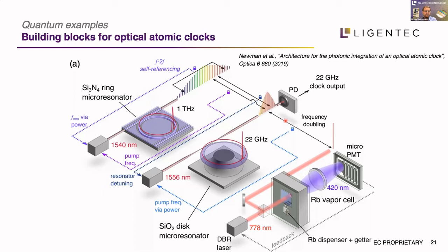So this is on a silicon nitride platform. Such a resonator at the moment is still in a silica platform, but can also be integrated in a silicon nitride platform. There are efforts that we have to integrate the photodiode on our platform, and also to get several wavelengths on one chip. And here silicon nitride has a true advantage, because it is transparent from 400 nanometers up to 3 to 4 microns, so you can propagate several wavelengths on one chip.